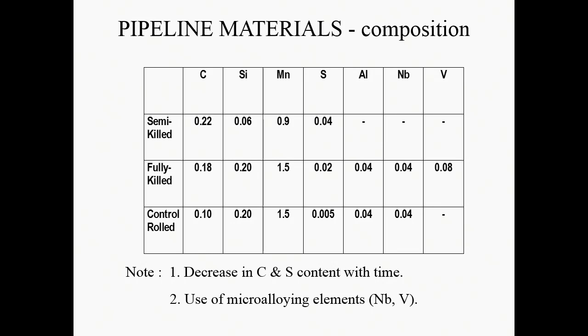Let's look at steel development. This is just the composition of 3 different steels. This is the original semi-killed steels, the fully killed steels that were developed for continuous casting, and then the control rolled steels. Same grade. So you can see the composition has changed. What's happened over the years?